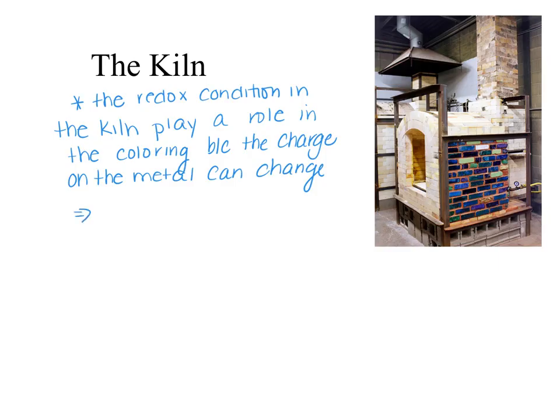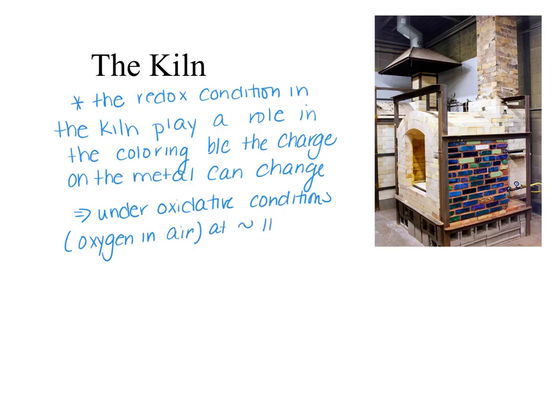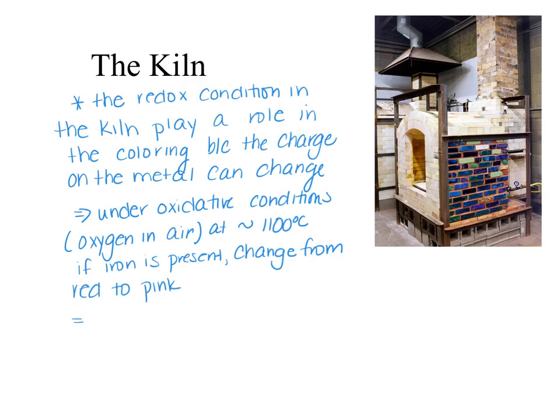So, right, under oxidative conditions, which is oxygen in air, is how that's defined, at about 1100 degrees Celsius, if iron is present, you'll see a change from red to pink. And so that's an example of a change that you would see, right?